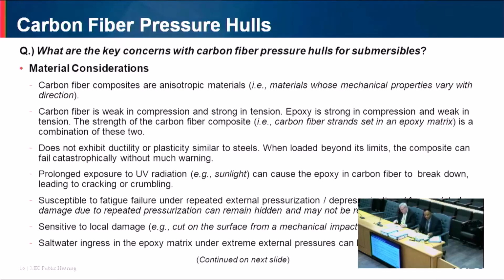So the first thing is carbon fiber composite pressure hulls are anisotropic. That is, the mechanical properties vary with direction. The mechanical properties are strongest in the direction of the fibers. When the fibers are loaded in tension, that is when the carbon fiber composite is the strongest. But if you go in other directions, the composite is not so strong. So when the composite is exposed to external pressure, the pressure will act perpendicular to the direction of the fibers, and that is not the strongest direction of the carbon fiber composite. Okay? So this is very different from traditional materials such as steel or titanium, which are isotropic. That is, the mechanical properties are the same in all directions.